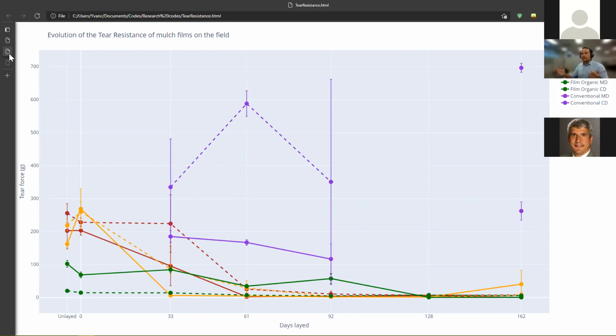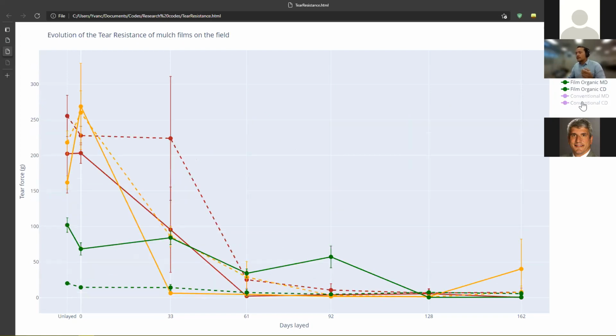Then another key property that the professor mentioned was tear resistance. Tear resistance is very important when laying the material. But once it's laid, as you see, all the plastics lost tear resistance after 2 months. That is okay because they don't need it anymore. It's just important when laying the plastic. But for our purpose as an indicator, it's not the best because after the 2nd month, all the plastics have very similar tear resistance, and that does not give us an idea of which is degrading more and why. But for the performance, it's good to know that after 2 months, all plastics lose tear resistance, and that's okay.